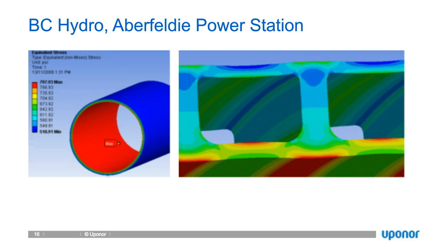And the highest stresses are usually found, as you can see in the illustration, the picture on the right, in the middle of the waterway wall. The waterway wall here is the one at the bottom of the page, and the stress that's highest is in the middle, and basically that's bending moment occurring across the pipe wall between the ribs. There's also a region of high stress near the ribs, highest really where the waterway wall meets the rib. So those are the two locations of interest.